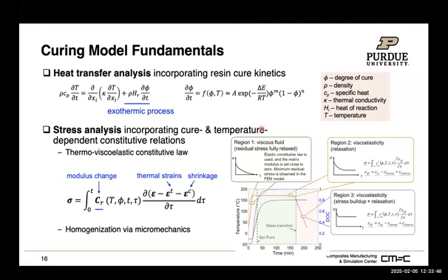And that heat generation will be characterized using cure kinetics, which we can measure in the lab using a device. On the other side, we also need to know how to incorporate those cure kinetics into the stress analysis by understanding the constitutive behavior, how the polymer evolves during that curing process. So I know most of you are not focusing on the mechanics, so I will try to keep it brief. But as you can see from the diagram, we actually have to see the transition of the polymer into different stages during the curing.